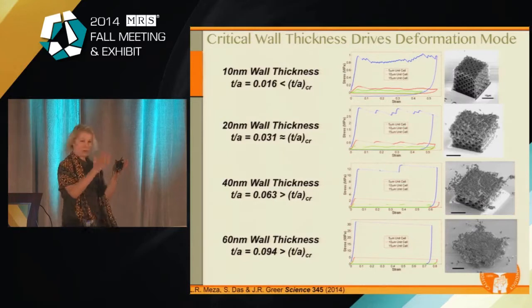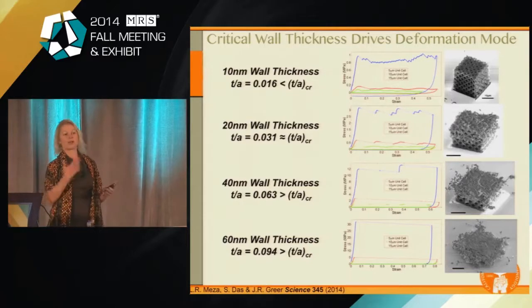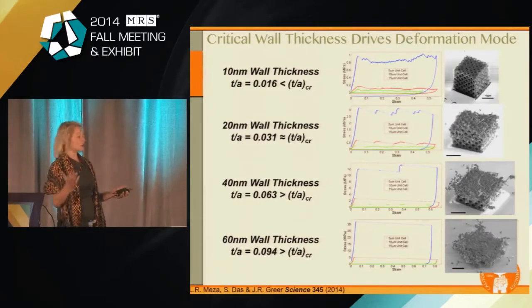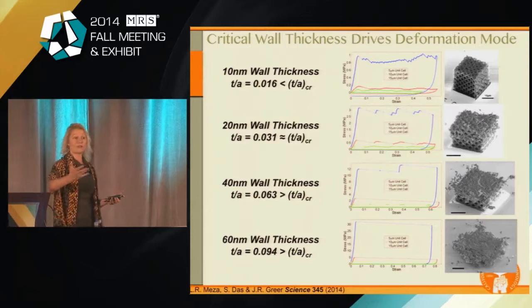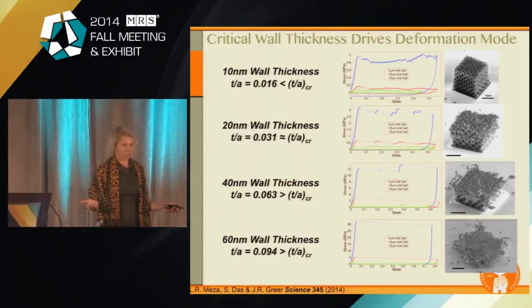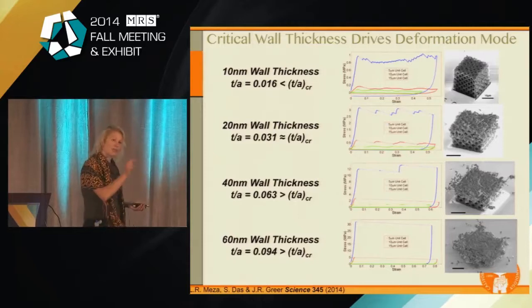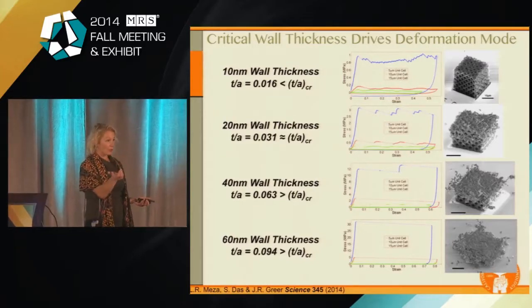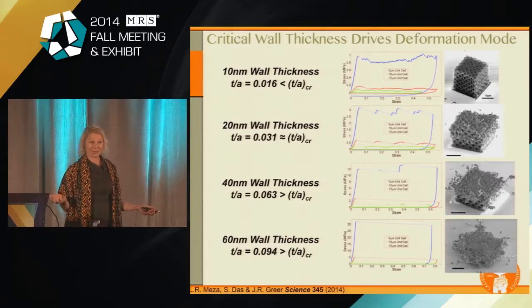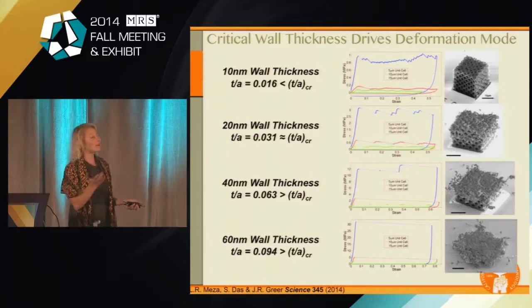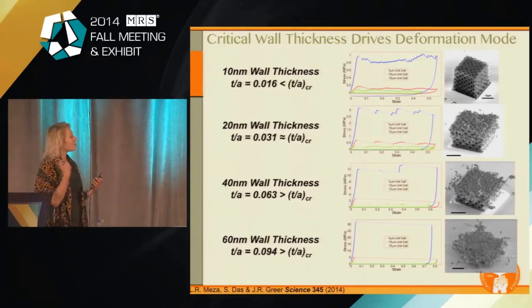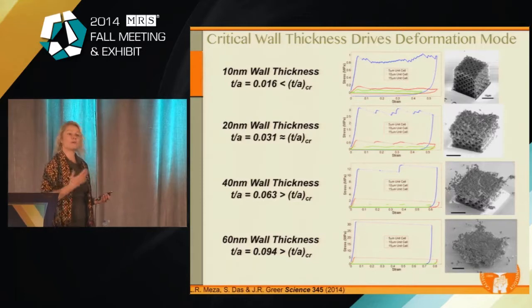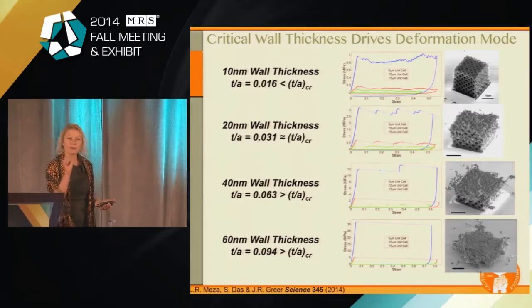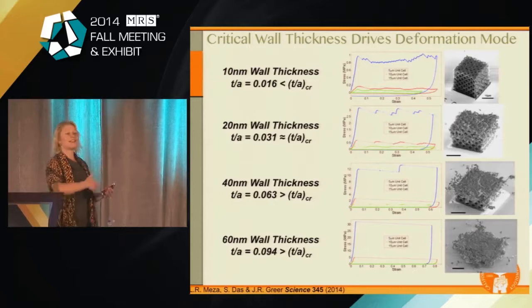So if you take a ceramic structure, a concrete structure, whose walls are 10 centimeters, the probability of finding a flaw in there, especially a weak flaw, is 100%. Absolutely, we will find many, many flaws, and then at those locations, the structure will fail before ever getting a chance to experience shell buckling. But in these structures that are only 10 nanometers thick, first of all, the size of the largest flaw is about 10 nanometers. Secondly, the probability of finding a flaw in there is reduced significantly. So the size effect manifests itself here in the sense of proximity to ideality. We're able to make much more high-quality materials in small dimensions much more readily than in large dimensions.